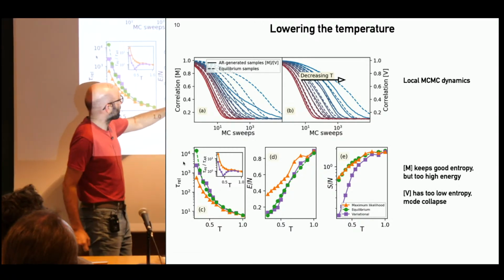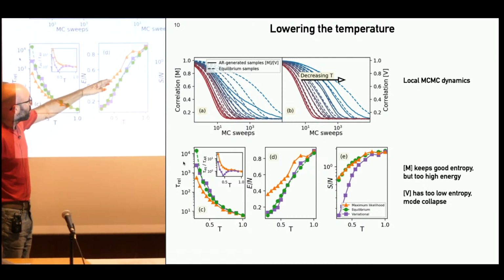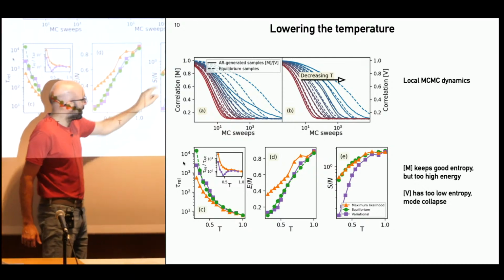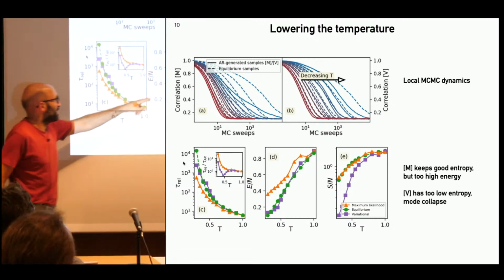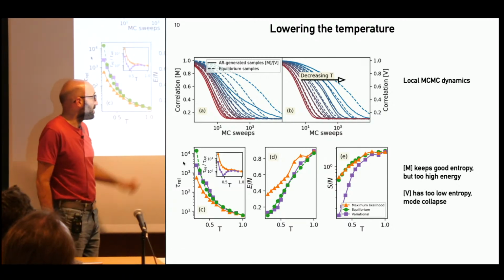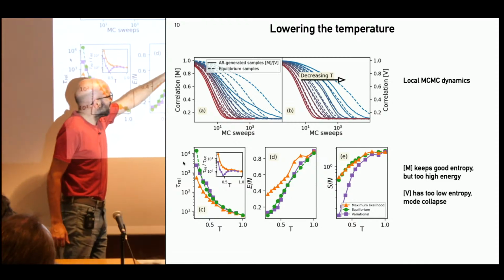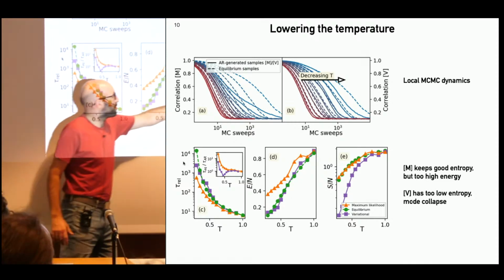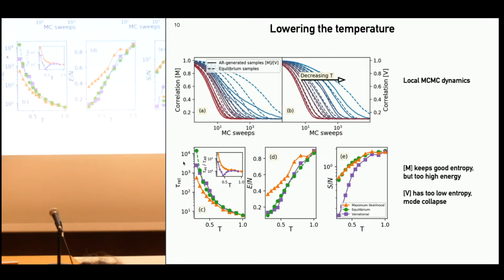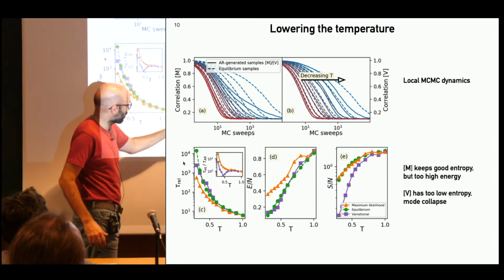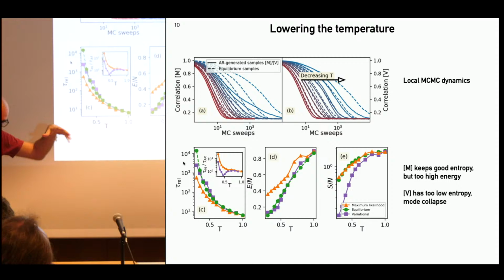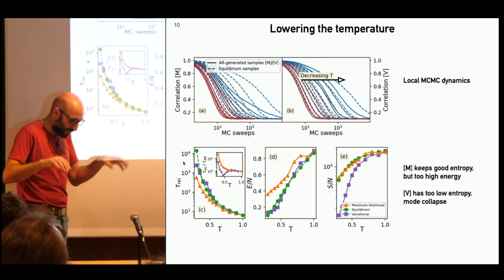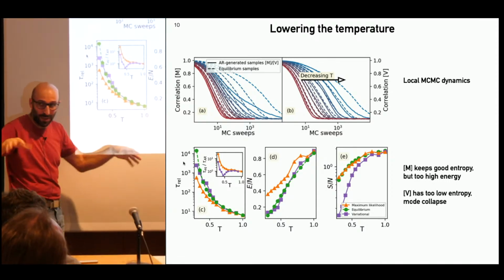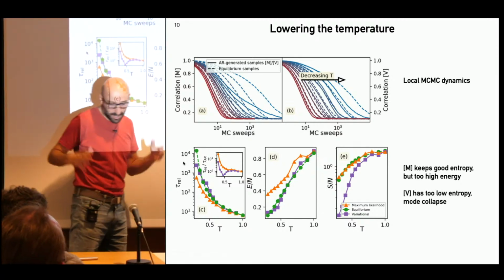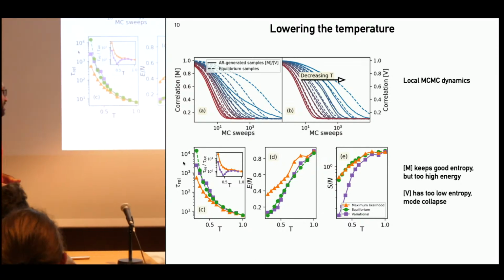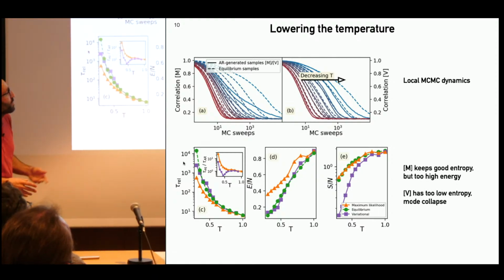The problem is that with maximum likelihood, when you lower the temperature, it keeps a good entropy, but it's not able to go down enough in energy, while the variational one is able to fit the energy well, but at the price of reducing the entropy. So it's kind of mode collapsing. Because the Boltzmann distribution, when you go down in temperature, starts to have all these local metastable states that give you local peaks of the probability, and probably the variational model is trying to learn some of them in order to keep the energy low. That's what we see.